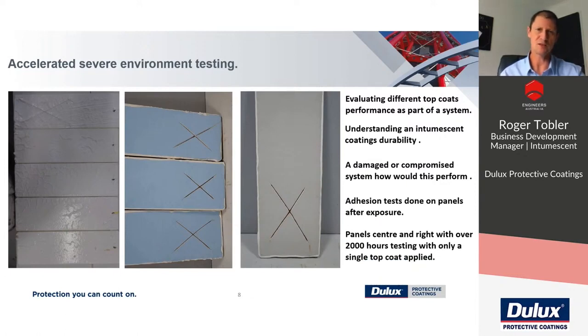So as I mentioned, 2,000 hours for the epoxy, and that's the 2 panels on the right. You'll find that with solvent-based intumescents, there's some literature out there that speaks about them, and they typically get 1,000 hours of exposure to severe environmental testing, and then they start to show some undercreep. So they do fare better than the water-based, but they don't compare to the epoxies.